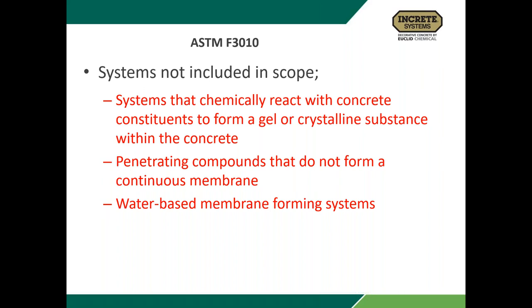And then water-based membrane-forming systems. You saw that it calls for a two-component system. The reason is that with most two-component systems, the way they react and form a film is they cross-link, which forms a much, much tighter film. Water-based membrane-forming systems that aren't two component coalesce, which forms a much more open film, and that film will typically allow more moisture vapor to transmit through it.